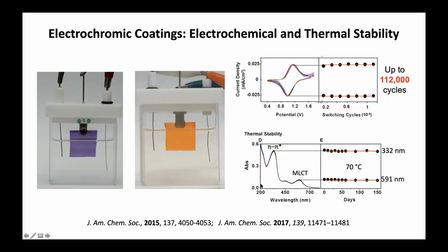This is a UV spectrum of such a film. You have the metal to ligand charge transfer band here that causes the coloration of the film. So heating the film at 70 degrees in air for 150 days, we don't see any changes in the optical properties of these films. Why 150 days? Because after 150 days, the paper got published and we moved on to another project. But the films are quite robust.